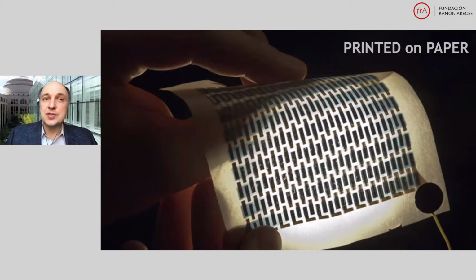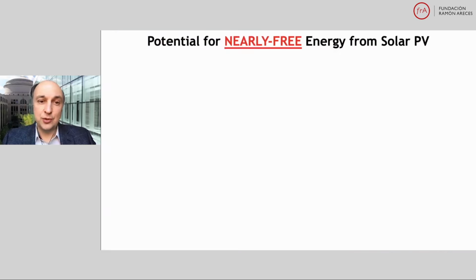Plastic that we use as a substrate to take our material is maybe 50, 150 microns in thickness. It's still too thick compared to the actual cell that's only 1 micron or 0.5 micron in thickness. So can you put such a cell on an even lighter substrate than plastic? Paper would be an obvious example. And the answer is you can. This is an image of one of the cells we deposited on paper.